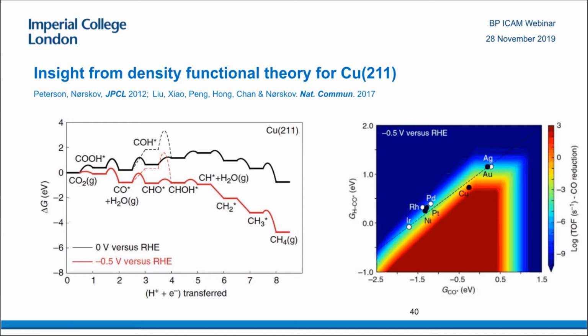So ideally, if you wanted to have really high activity and low potential losses, you want a catalyst to be here, but all pure metals fall on this curve. So we call this a linear scaling relation. Copper is closest to this red area, the high activity, but still not good enough.